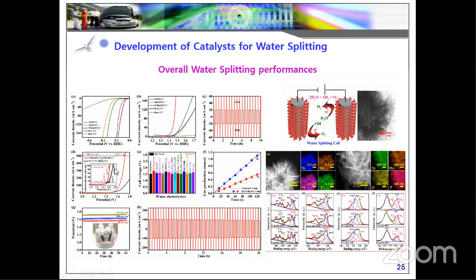Even at high current density, when we go for high current density, the commercial catalyst potential is very high, but our catalyst achieved around 500 milliamperes at 1.72. So from the studies, we can confirm our material is highly active even at high current density, and our catalyst is highly active towards the OER and HER, and finally achieved the potential of 1.51 for overall water splitting, also better than the reported catalysts.